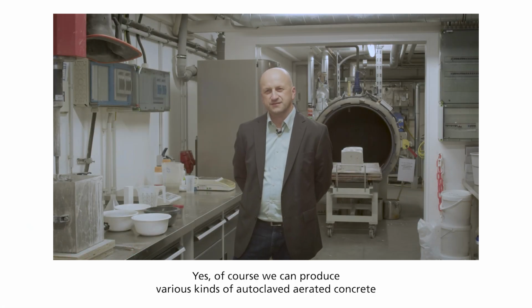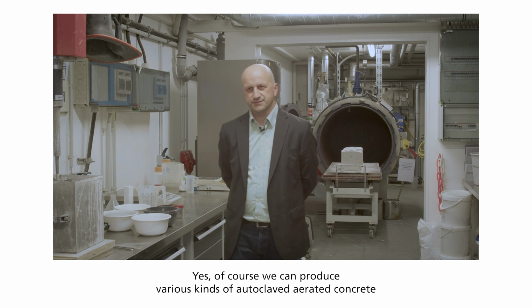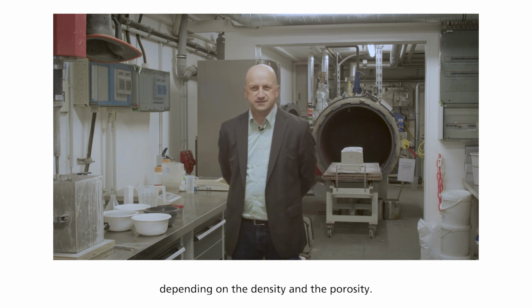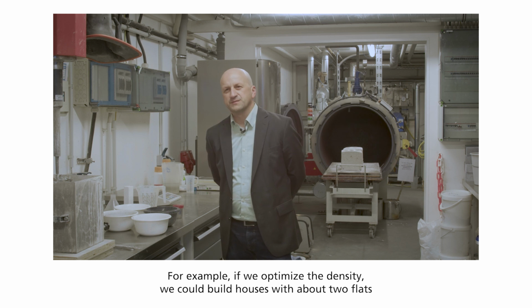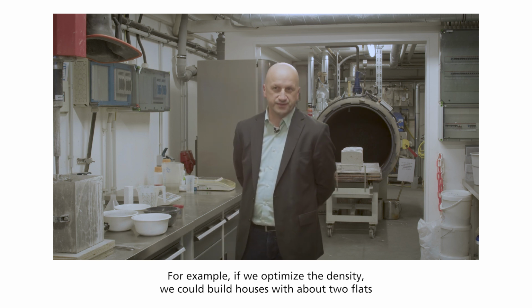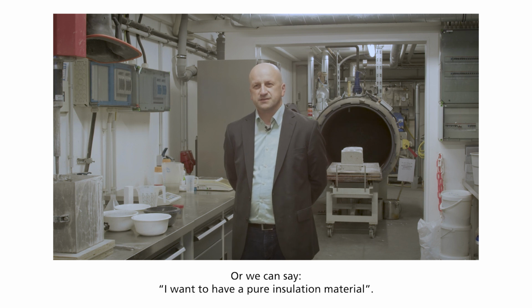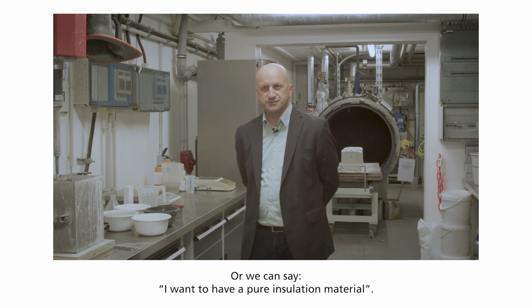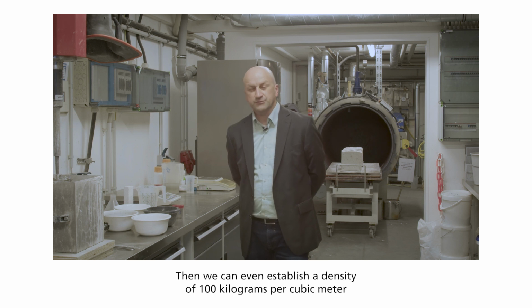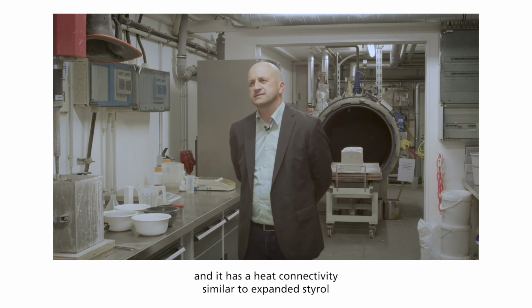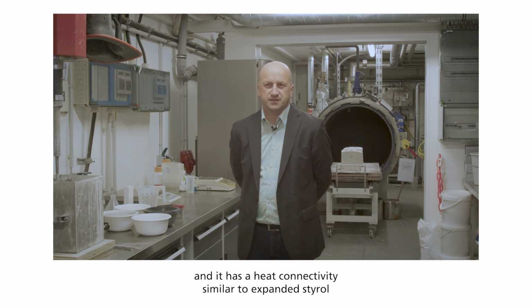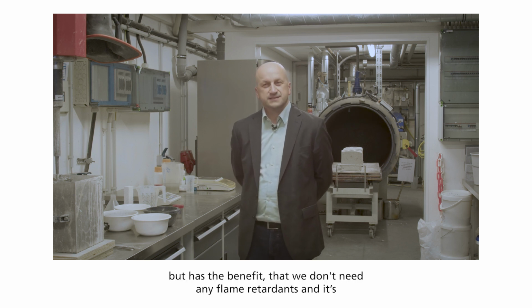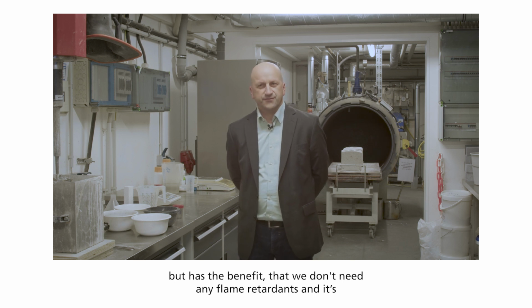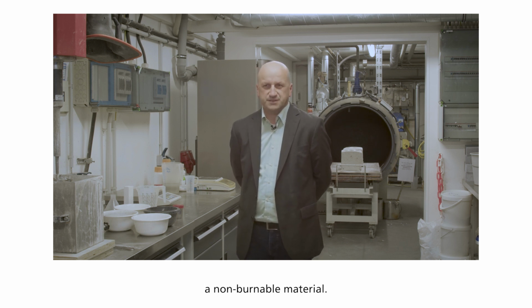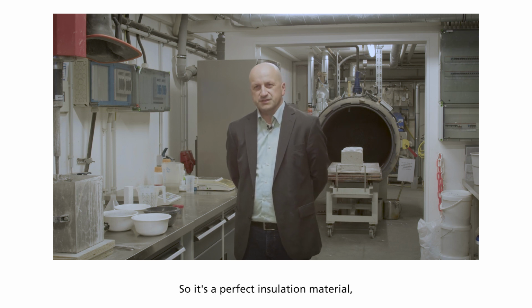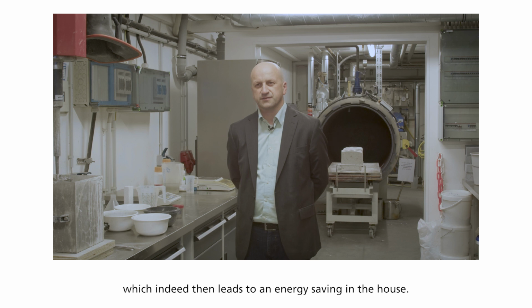Yes, of course, we can produce various kinds of autoclaved aerated concrete depending on the density and the porosity. For example, if we optimize the density, we could build houses with about 2 flats with this material. Or we can say, I want to have a pure insulation material. Then we can even establish a density of 100 kilograms per cubic meter. And this has a heat conductivity similar to expanded polystyrene, but has the benefit that we don't need any flame retardants, and it's a non-burnable material. So it's a perfect insulation material, which indeed then leads to energy saving in the house.